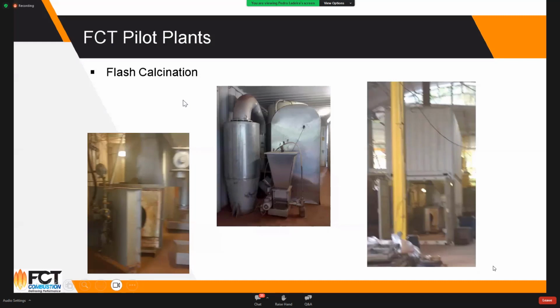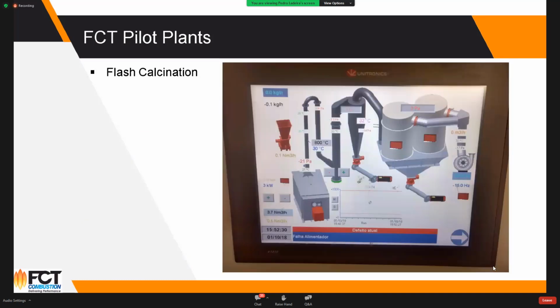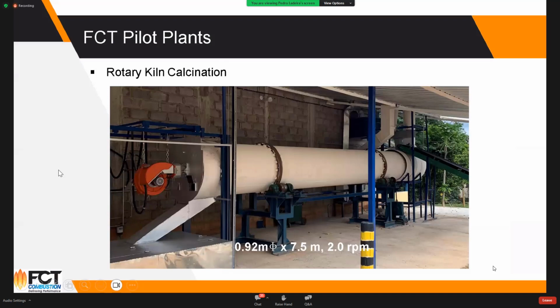So we can provide you with pilot plants. We have a flash calcination in Brazil. It's a flash calciner mounted in 2 containers. It operates, and we've been doing a lot on this for scale up and to provide solutions for our clients. It's basically a hot gas generator, a calciner loop, and then we quench the material with air and get product from it. And we also have a rotary kiln calcination. It's a sizable pilot plant. So we can submit your product for testing in our facility, so we can have the proof and collect the data needed for the scale up.